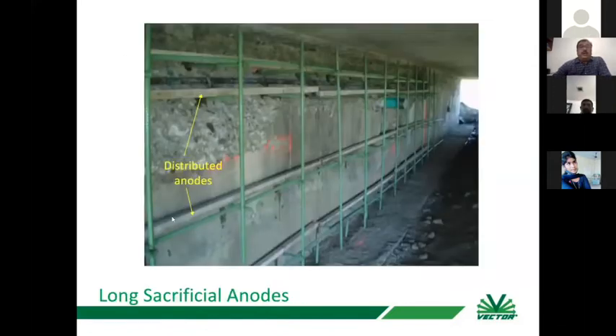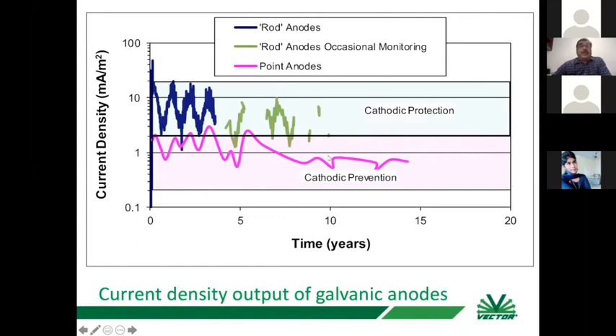There can be a longer, similar discrete anode which can give you a higher current. It can be distributed anodes, a longer strip anode which you can install when there is a high density or high amount of steel, or there is high contamination. Then you have a higher current requirement, so we need longer anodes. The discrete point anodes, the pink line, have a lesser current, which is good for prevention. When it comes to cathodic protection, a longer rod anode gives you very high current as per the requirement, and it functions wonderfully.